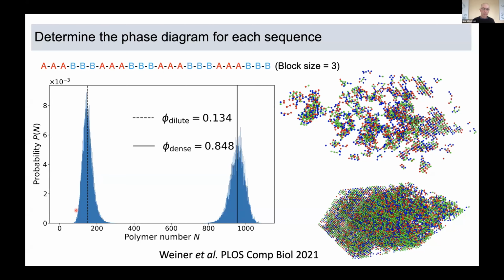And so when we keep track of what the system is doing, we'll find this histogram with these two peaks. Sometimes it's down here with 150 polymers distributed in the system, and sometimes it's up here looking like this with more like 900 polymers. And from doing this and from balancing the weight of these two so that we know we're actually right at the point where we've defined a system with equal free energies in the dense and dilute phases, we can extract from the mean of these what the densities of the dense and dilute phases are. And from that, we can then generate the phase diagram that you're sort of waiting to see, with the two-phase region.